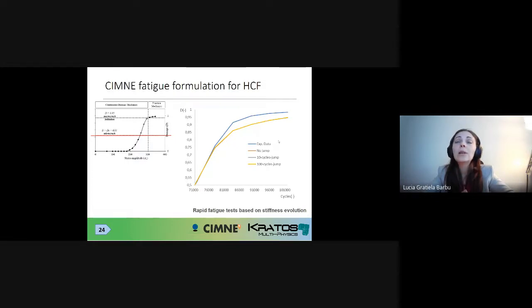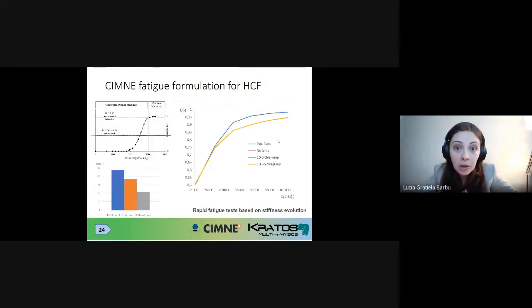Why? Because when you do this simulation, applying the load 100,000 cycles, cycle by cycle, you are going to be spending a lot of time with this, basically about 24 hours. And we wanted to see, okay, what happens when we use cycle jump strategies? How are we able to reduce the computational time? And you can see here, for instance, with a jump step of 100 cycles, we are managing to lower the computational time to 10 hours. And this analysis can be further pushed down in terms of computational time.